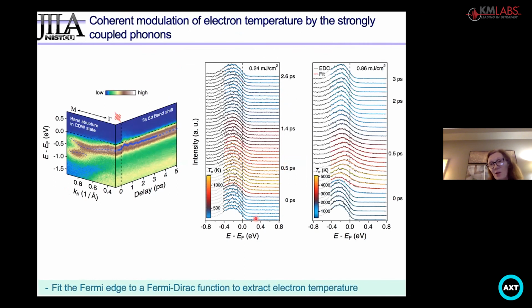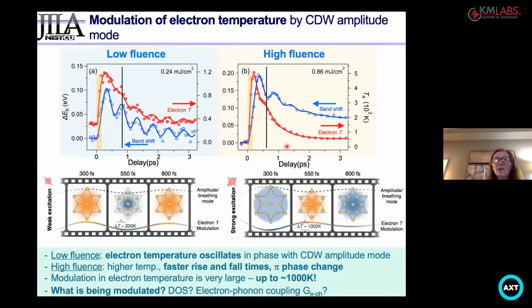This is photoemission spectra at the Fermi level as a function of time. And when we translate that into an electron temperature and a band shift map, what we see is something very surprising. We see that the electron temperature is oscillating in phase with the amplitude mode, the strongly coupled phonon mode. And these temperature oscillations are quite high. They go between 200 Kelvin and 1,000 Kelvin.